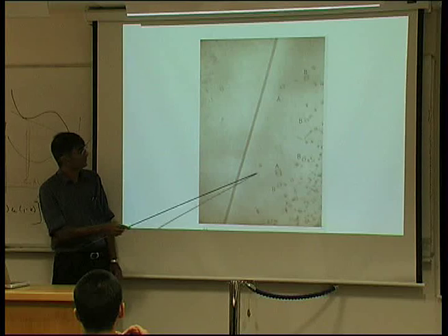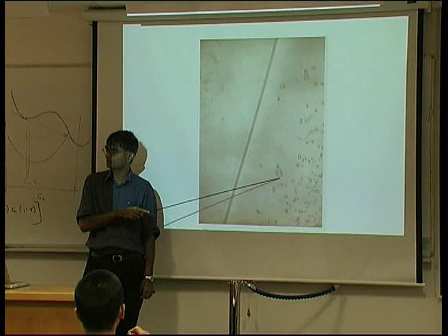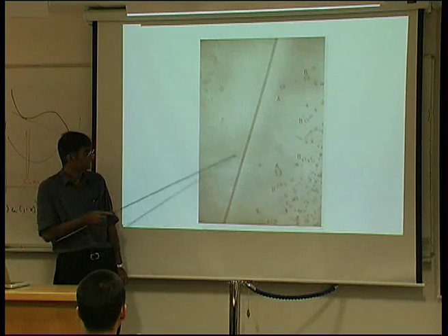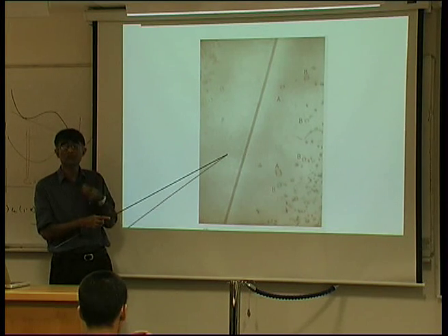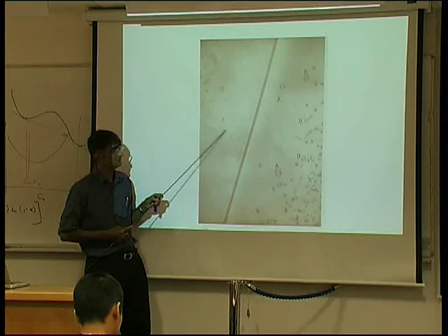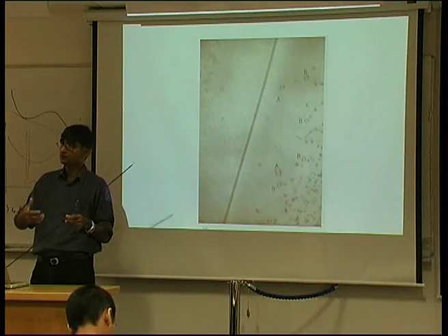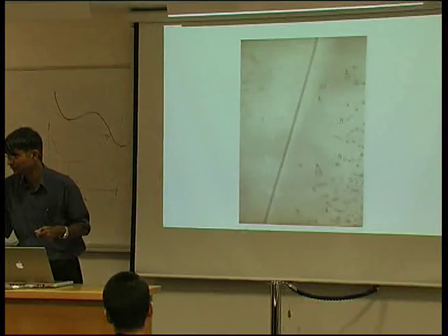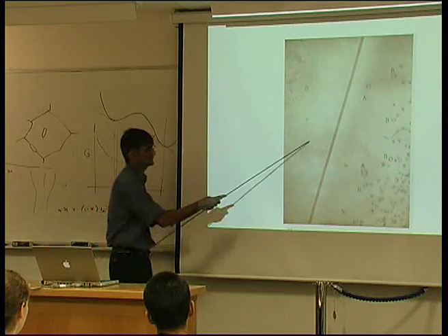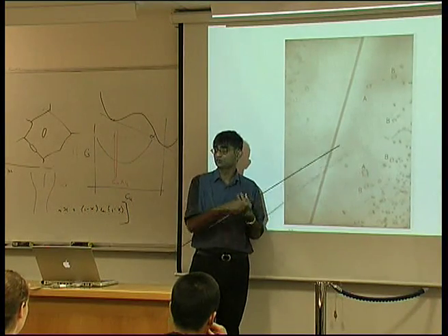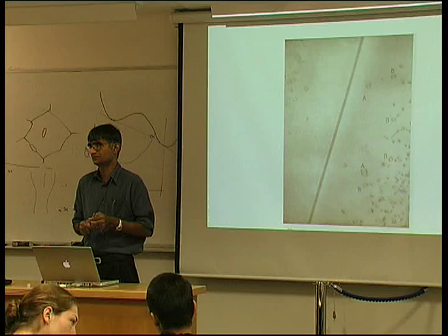But there are no dislocation loops in the vicinity of the boundary. Now these are good nucleation sites for precipitates, but we can't nucleate precipitates here because we don't have defects to nucleate on. So when precipitates start to form, even if there is no solute depletion here, you won't get precipitation. Okay, because there is a depletion of vacancies, which are defects, which help to nucleate precipitates. So this is a case where we do have excess solute here, but we don't have the vacancies, which have sunk into the grain boundary, to help nucleate the particle.